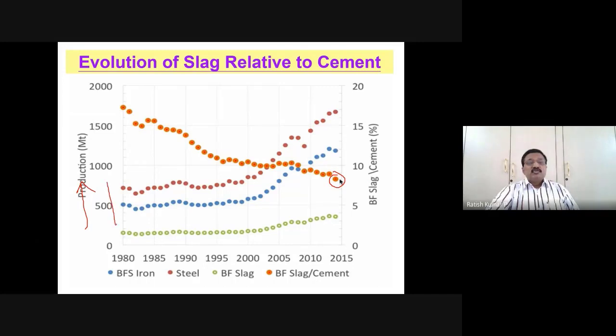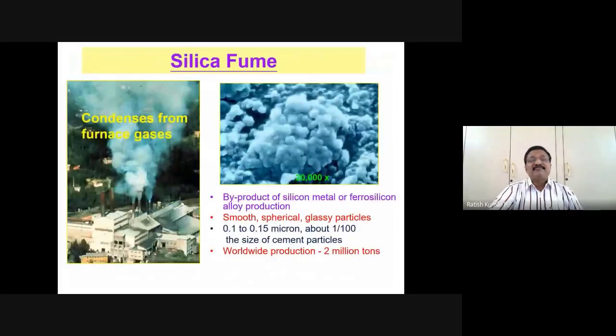We require using a lesser amount of fly ash, because these days we are talking about very high or quick setting, or concrete which has to give results in a very short time, but the amount of fly ash available is more. The use of fly ash should be reduced in the sense that there should be a check on that, otherwise there is going to be a problem. Slag can be used more, but the bad news is that only 8% is available across the world, and that is the reason why we have to think about binary, ternary, tertiary supplements, the different types of combinations of these materials. That is how the concept of alternate materials or combinations of materials has come.